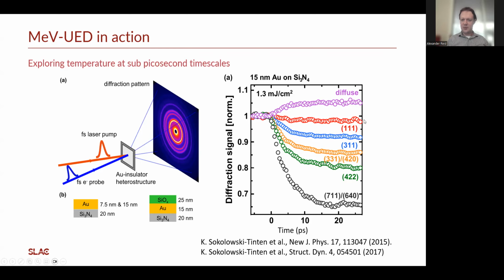As you can see, as we go from low momentum space transfer reflections, so this is the 111 peak, which is near the center here, going out to these outer peaks, the relative change in intensity gets more and more significant. And this is following the well-known Debye-Waller dependence on these intensities. And from this, we can actually extract the mean square displacements of the atoms as a function of time.